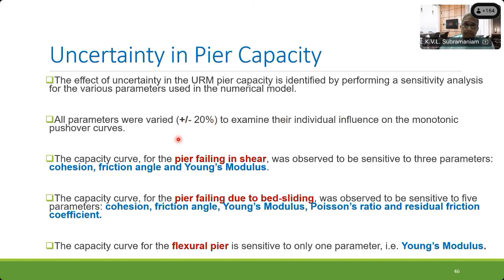Now, to do that, we considered the important material parameters, and we varied the parameters about plus or minus 20% of the mean to see which of these are sensitive parameters. And we found that when you predict the capacity curve, the monotonic push curve, for a pier failing in shear, it is sensitive to cohesion, friction angle, and Young's modulus of the brick. Similarly, piers failing in bed sliding depend upon all 5 parameters, and those failing in flexure only depend upon the Young's modulus of the brick. These are the sensitive parameters.